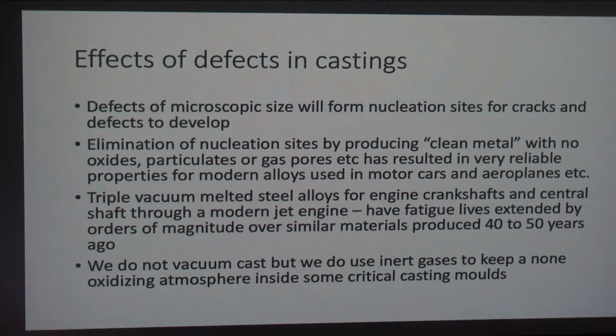So, the reason why we don't want defects in these castings is because it causes a lot of problems. It is defects on a microscopic scale that cause nucleation sites for cracks and defects to develop. And the elimination of these nucleation sites can only be achieved by having what we describe as clean metal. That means, as I said earlier, there's no oxides, no particulates, no gas pores, just very clean metal. And a lot of this has come to be recognised, quite frankly, only in the last 50 to 60 years.